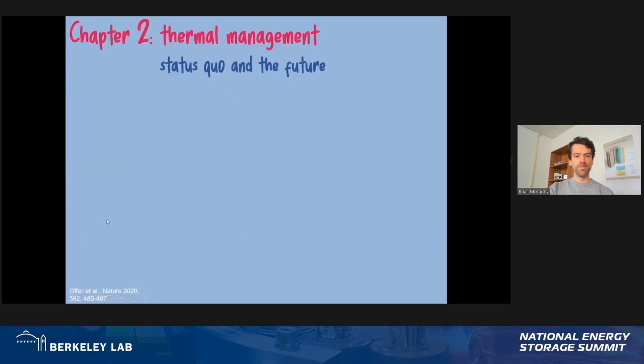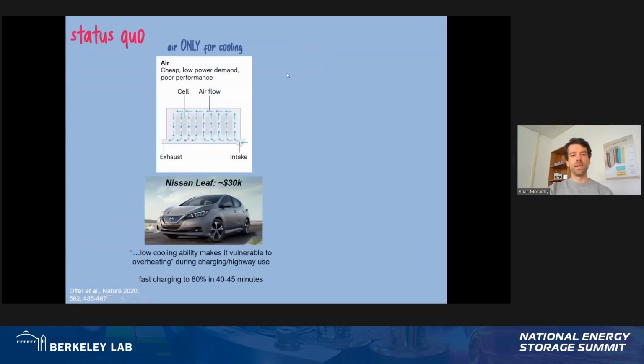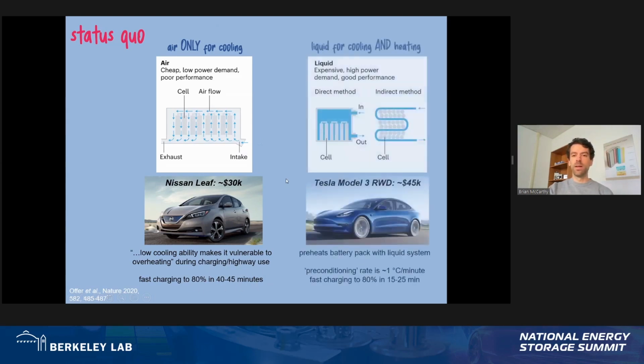So, chapter 2. The status quo consists of 2 general strategies. The first is air-only cooling. This is a very cheap method of cooling, however it is low performance. So this is utilized by the Nissan Leaf. And the low cooling ability means that it has real problems during highway driving and fast charging. Also, because you can't actually heat the pack using the system, it takes you much longer to fast charge. The more expensive and fancy option is liquid cooling and heating, as utilized by the Tesla Model 3, for example. Now, because you can actually heat your pack, you can fast charge in a much quicker time.